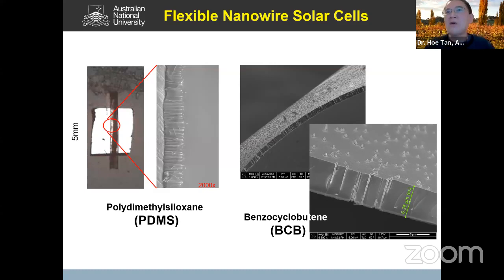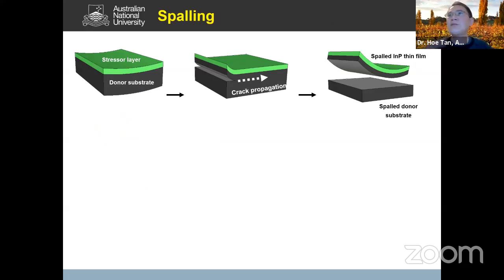So as the theme of this conference is on flexible devices, we are also developing a couple of other fabrication techniques to make flexible devices. So shown here is one of the techniques we are developing called spalling. Okay, the concept of spalling is demonstrated here. So you have your substrate, okay, and you put a stressor layer on top. Typically, this is a layer of film, a metal film, around a micron or a few microns thick, okay? So because of the stress that is created by this metal layer, okay, it bends up the substrate and creates a crack, okay?